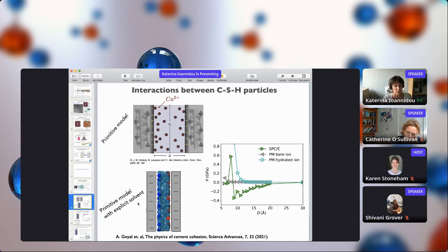In this type of primitive model that we propose, we introduce an explicit solvent. So we are using explicitly the water. If we use a hydrated ion for the calculation of the pressure, corresponding to an ion with a larger size, we get a pressure different than the one we calculate without the hydrated ion, but it's still not correct for cement.